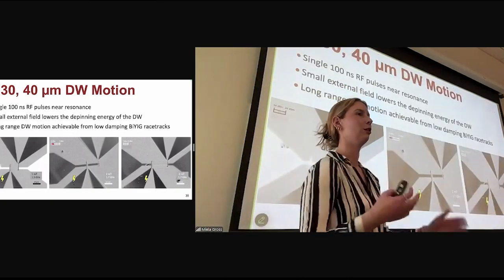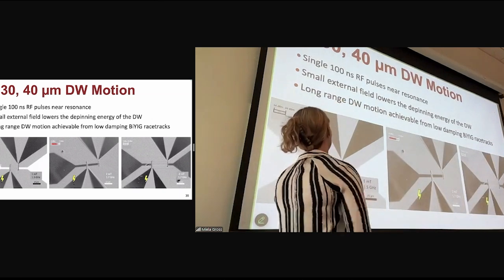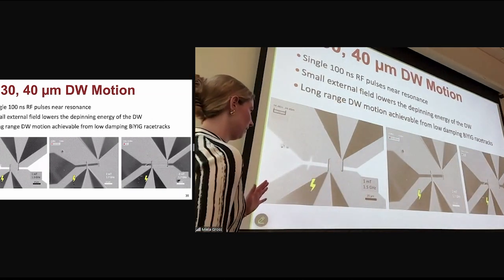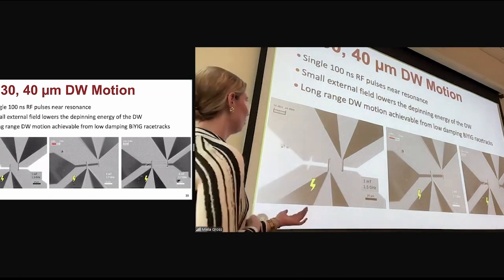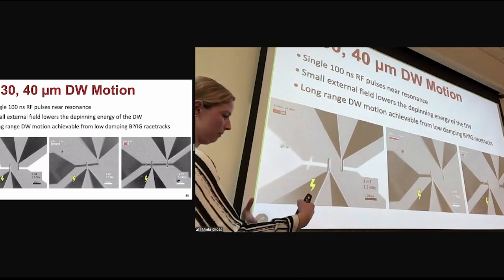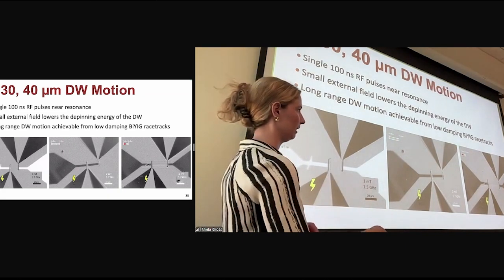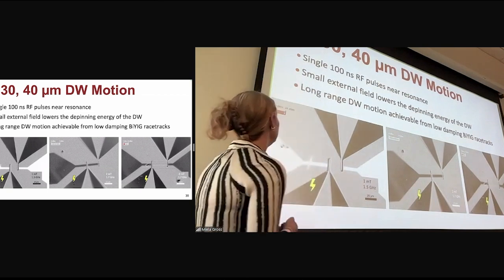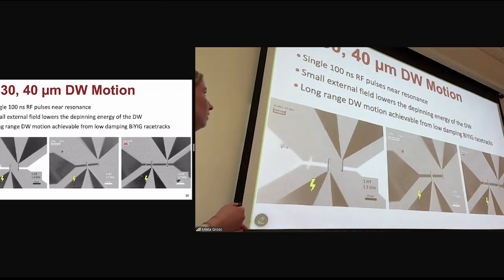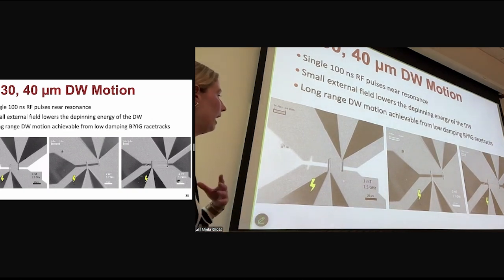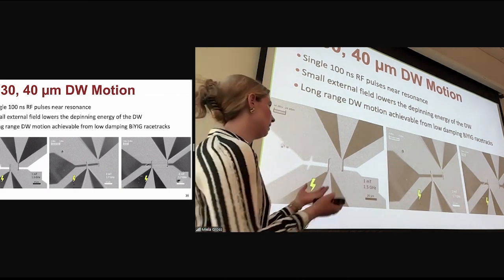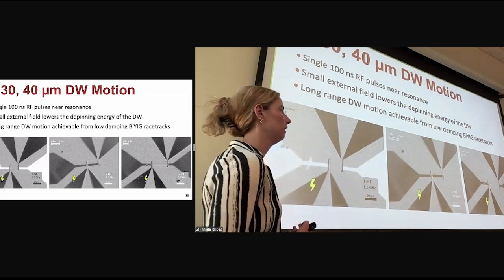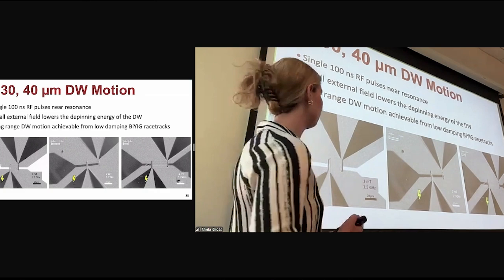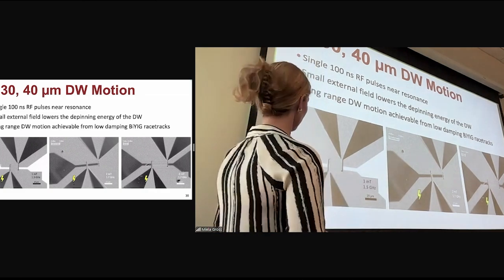And I said that I could see more long-range interactions, so that's what this slide shows, which is domain wall motion from spin waves. It shows domain wall motion in devices spaced 20 here, 30 here, and 40 microns apart. And these are all spin waves excited from 100 nanosecond RF pulses near the resonance of each film, and that's labeled in each movie. And we add some small external fields too, and what those external fields do, we hypothesize, is both lower the depinning energy of the domain wall, as well as increase the spin wave speed to aid in that domain wall motion.